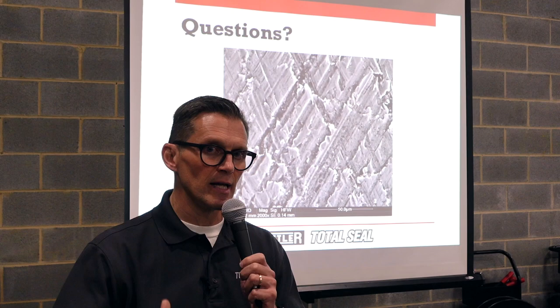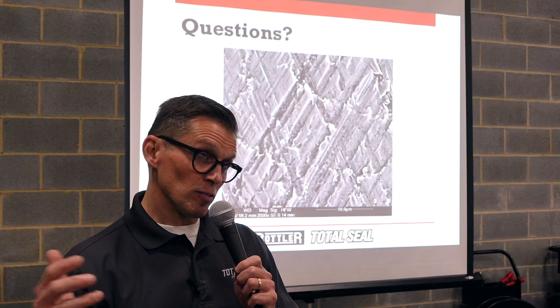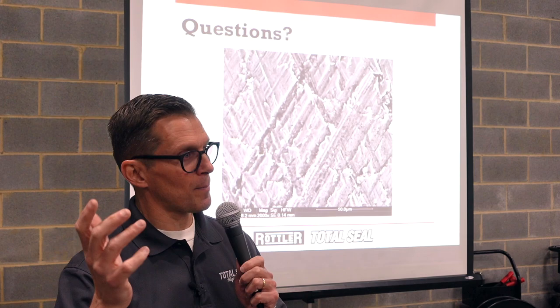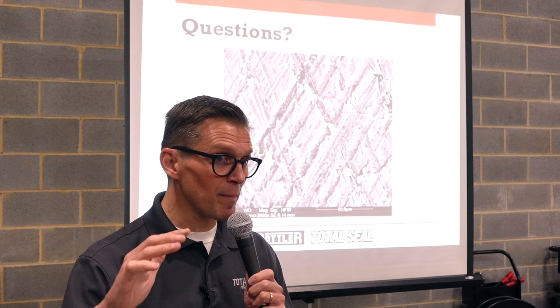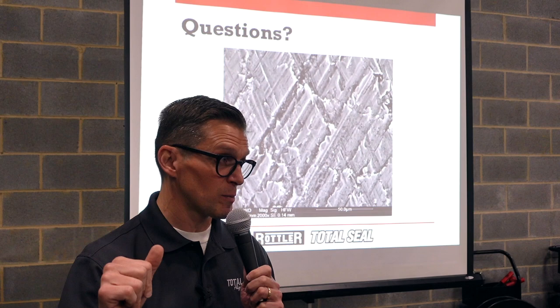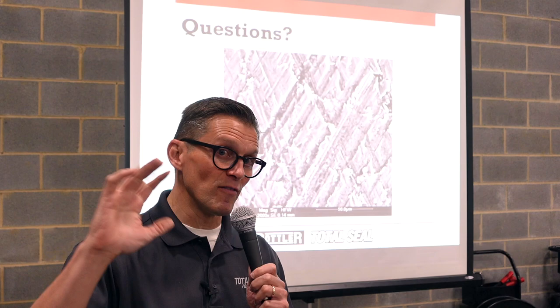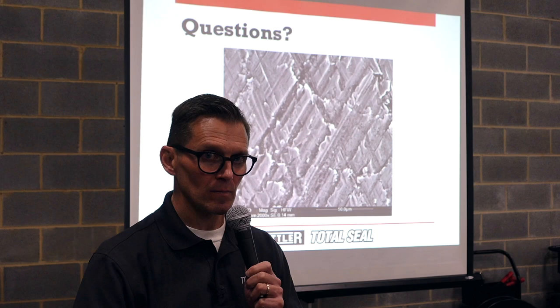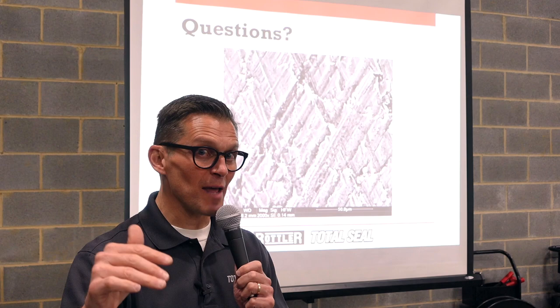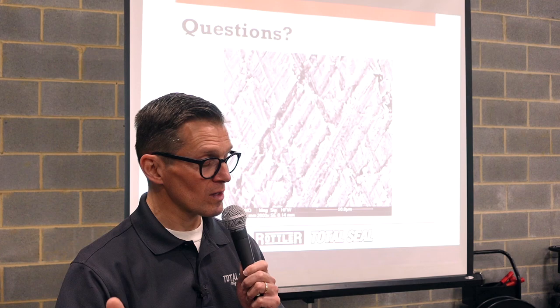What used to be pretty much all calcium would be in the 2,700 to 3,300 parts per million range in the oil. Well, if you have more than about 1,500 to 1,600 parts per million calcium, it will cause low-speed pre-ignition. So they've chopped the level of detergent in the motor oil in half, or more than half. But the ZDP level stayed the same. So what did it do? It made the ZDP that's already in the oil more effective. So the SP oils are actually better.